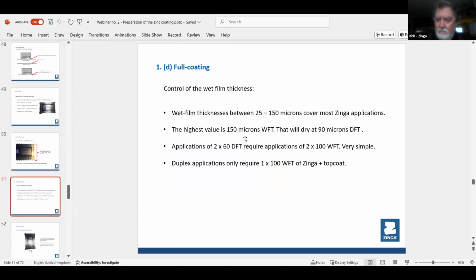So this is the wet film thickness. Your range is from 25 to 150, and that will cover most of your applications that you do with Zinga. As I said, 150 is the highest that you normally ever use, and that'll dry at 90 microns. You can apply 2 coats of 60 to get 100 microns. A lot of people will apply two coatings of 60 to 75 at the coast. That's normally your normal range. And instead of doing 1 heavy layer, they apply 2 at 60 because it dries faster.